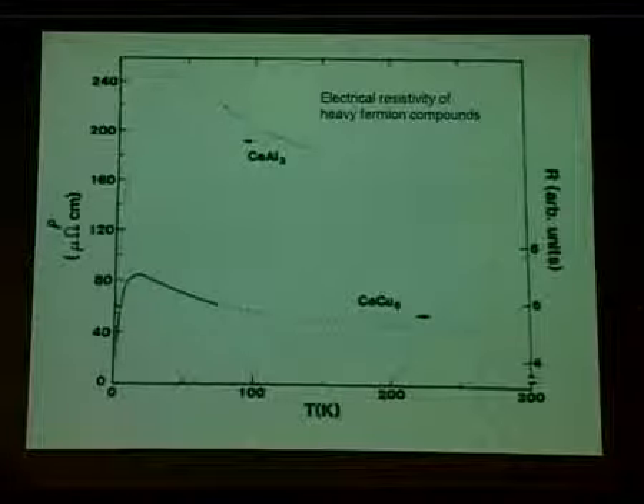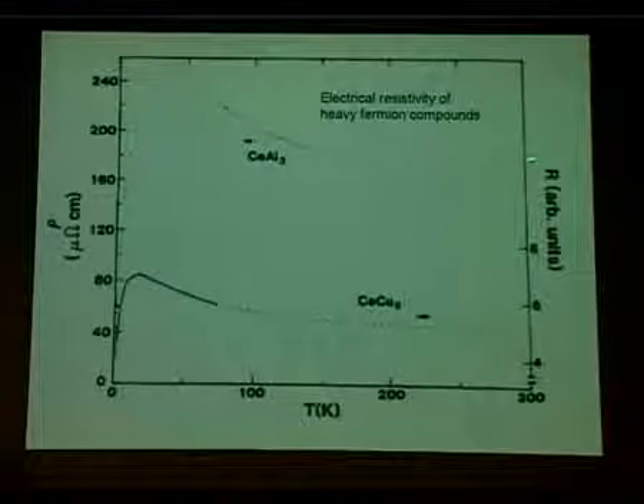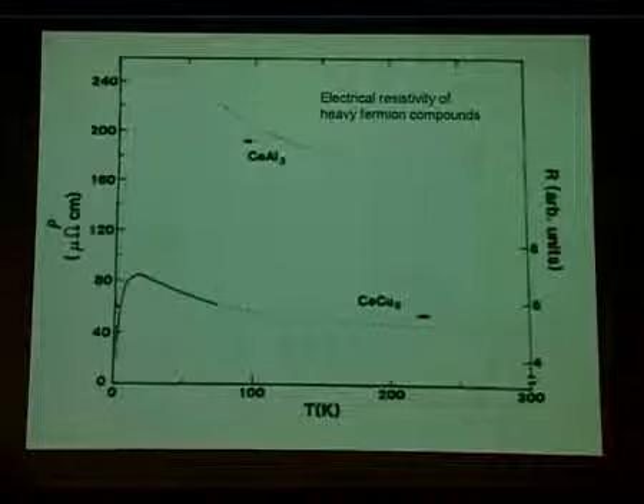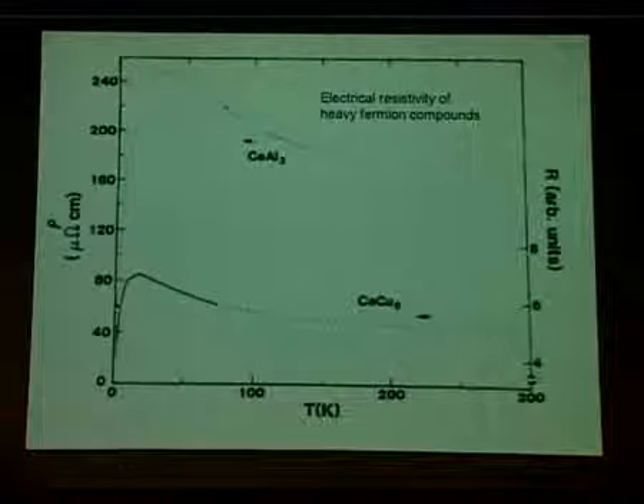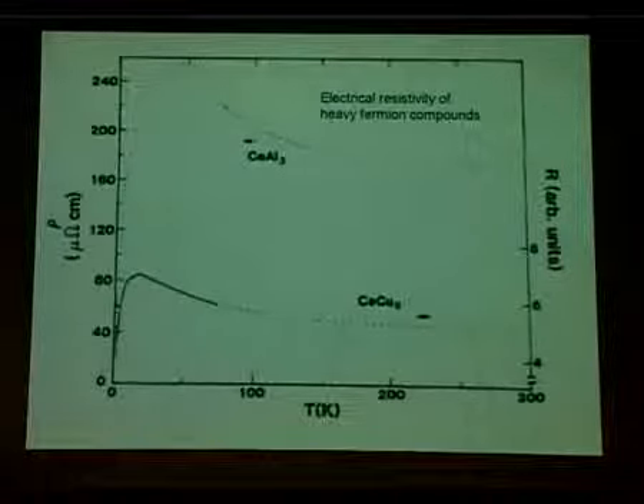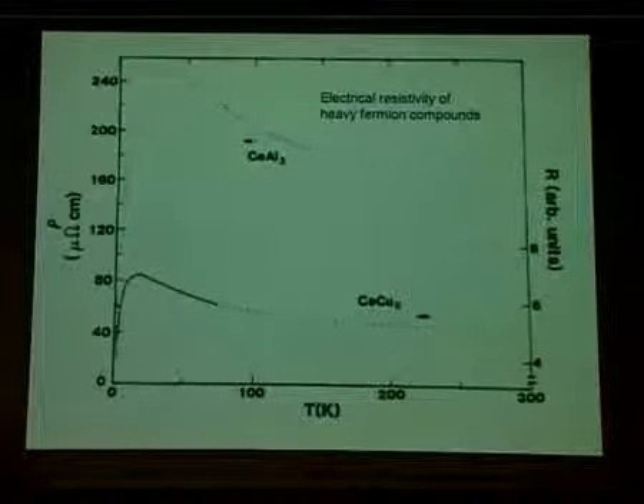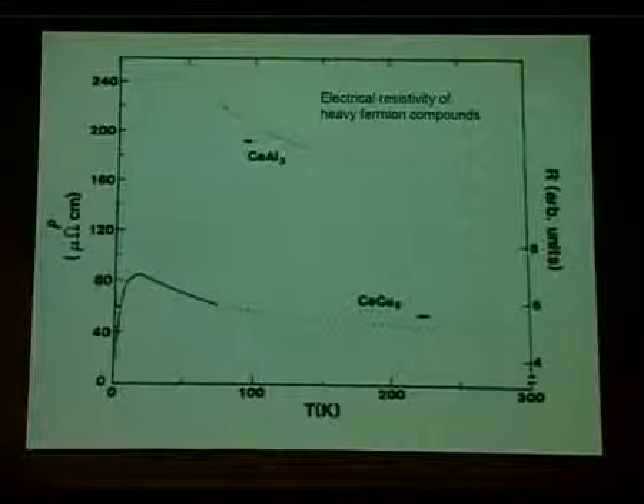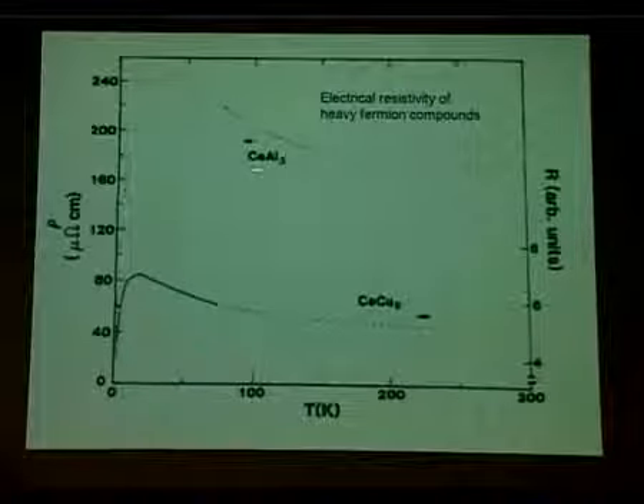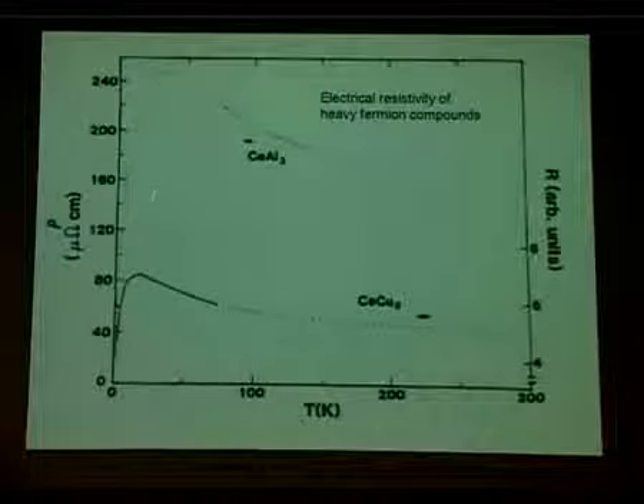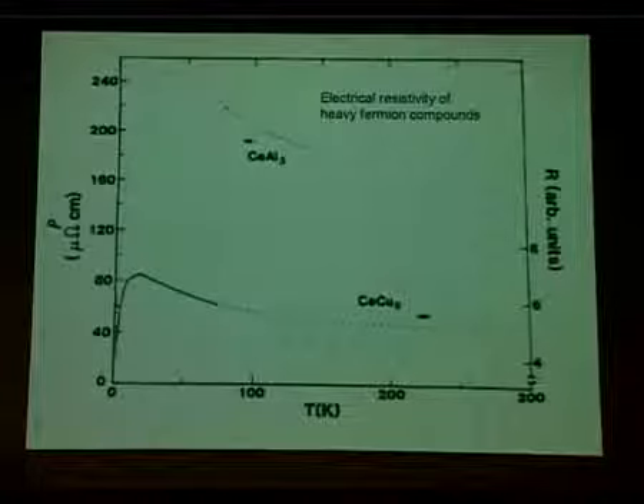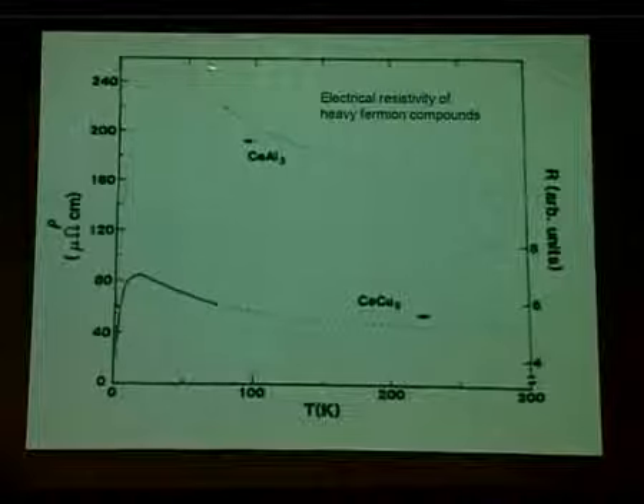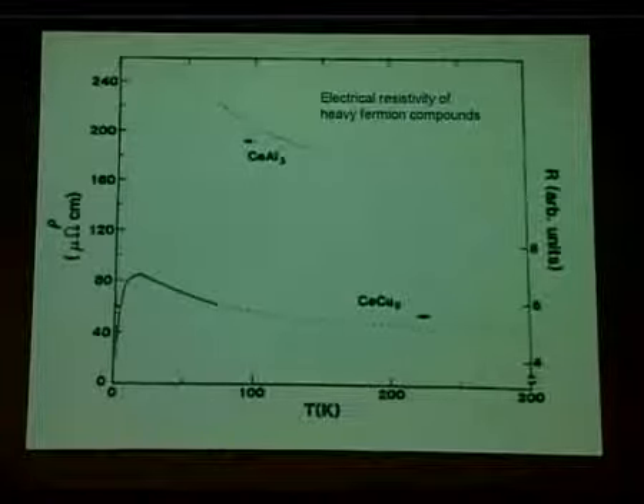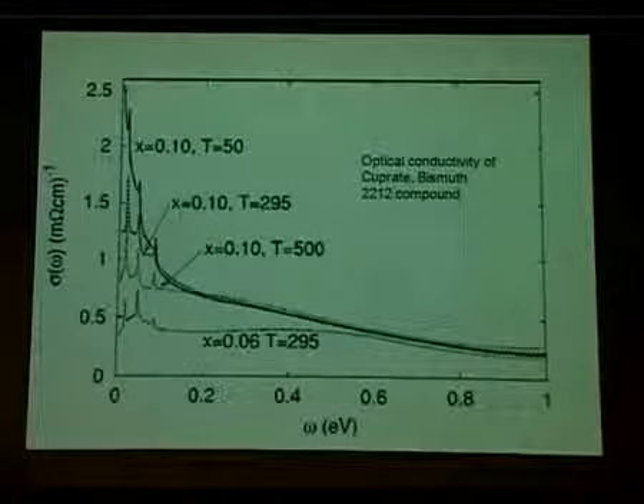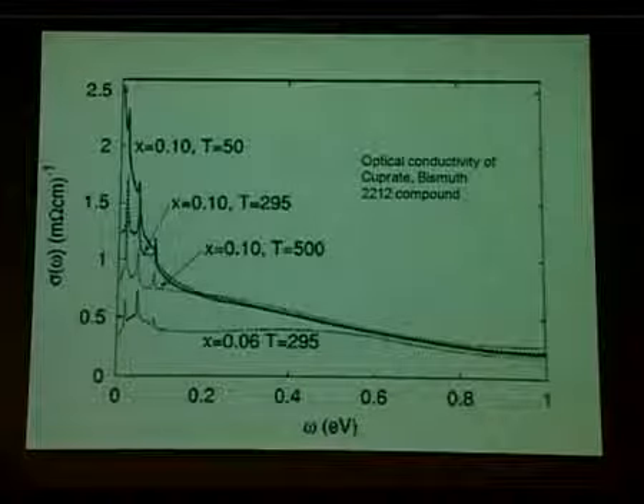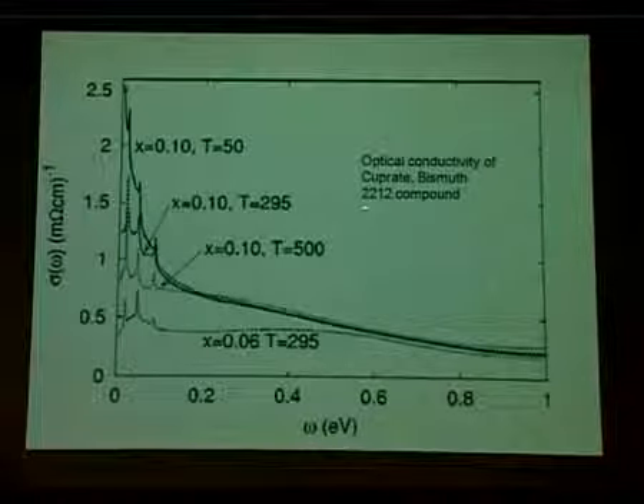Having a non-zero value of resistivity which doesn't depend on temperature would be all right if temperature is irrelevant. For example, suppose the system was a collection of incoherent scatterers, located here, there, etc., completely randomly, and the electrons move through it and get scattered randomly, and so they get some resistivity, and this arrangement doesn't depend on temperature. So it becomes quite incoherent. That's one interpretation, but it becomes incoherent at a particularly low temperature. So there is an incoherent region, there is a coherent region, and there is a crossover temperature. Okay, this is another example of the same thing. This is the optical conductivity of a cuprate, copper oxide. It is called bismuth 2212.